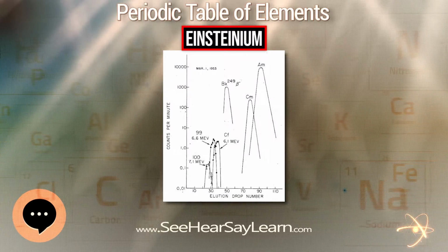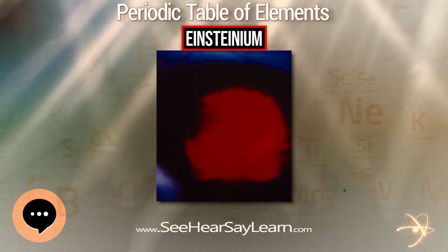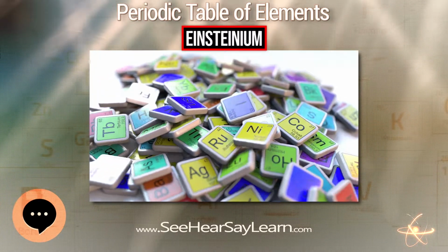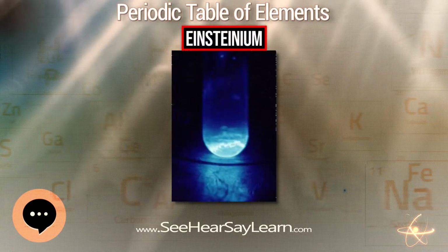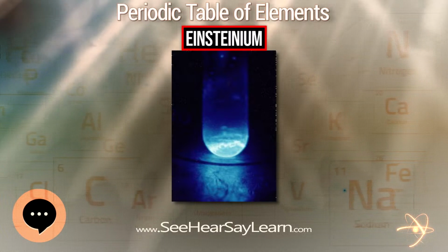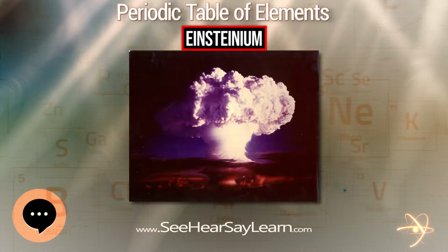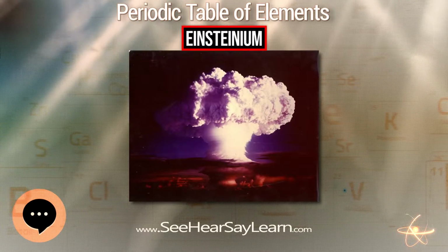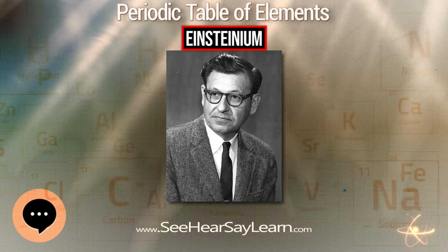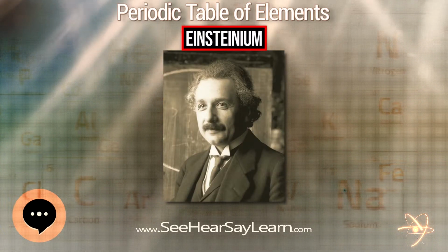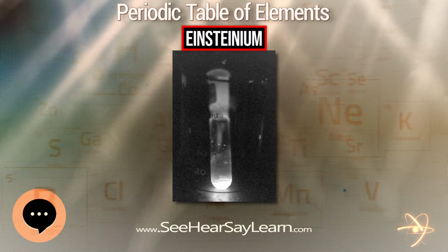Apart from the self-destruction of solid einsteinium and its compounds, other intrinsic difficulties in studying this element include scarcity. The most common 253Es isotope is available only once or twice a year in sub-milligram amounts, and self-contamination due to rapid conversion of einsteinium to berkelium and then to californium at a rate of about 3.3% per day. Thus, most einsteinium samples are contaminated, and their intrinsic properties are often deduced by extrapolating back experimental data accumulated over time. Other experimental techniques to circumvent the contamination problem include selective optical excitation of einsteinium ions by a tunable laser, such as in studying its luminescence properties.